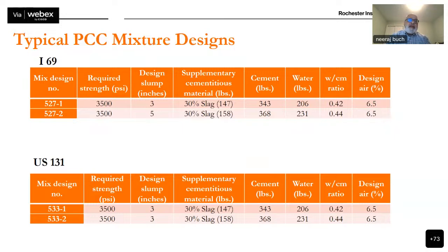There is nothing significant about this mix design other than this did have supplementary cementitious material. It did have granulated blast furnace slag that was mixed with type 1 Portland cement. About 30% supplementary cementitious materials were used, which is quite typical for the state of Michigan when they construct a concrete pavement. So there was nothing very significant or eye-catching as far as the concrete mix design was concerned. But I thought I'd share the mix design with you just for the sake of completeness.